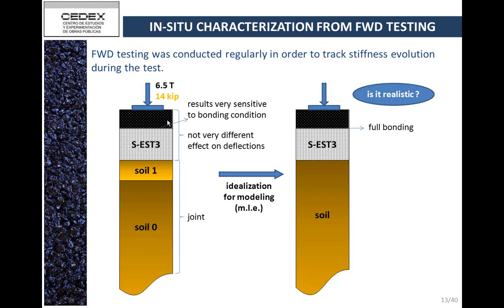And there is another concern which is related to the bonding condition between this layer and this layer. If you assume full bonding, then this structure will be very strong because these two stiff layers will be working together. If you assume that there is no bonding, then the structure will be very weak. But when you do back calculation, you have to assume a specific condition. So in the first place, we assumed full bonding. So this is the structure that we use in order to do back calculation.